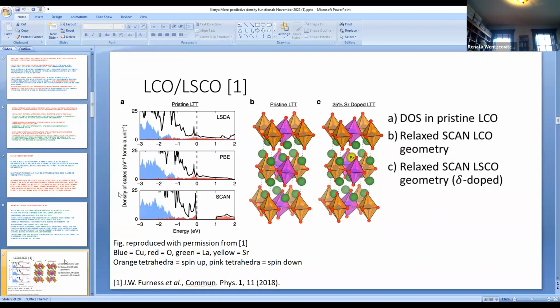You can see the structures of these materials. The structure of the pristine material is shown by the second picture. The copper atoms lie in layers, and each copper atom in a layer is surrounded by an octahedron of oxygen atoms. Between the layers, we have the green balls that are the lanthanum atoms. When we do 25% doping with strontium, we replace 25% of the lanthanums by strontiums. That's indicated schematically in the third picture.